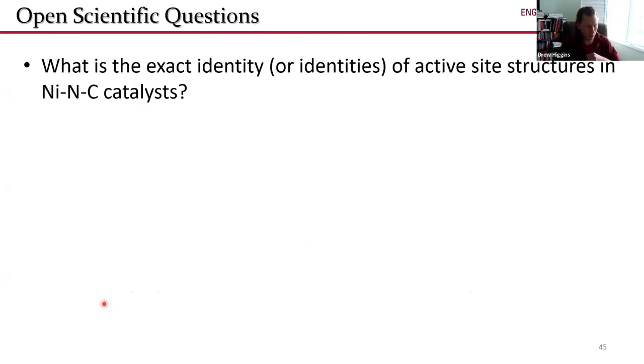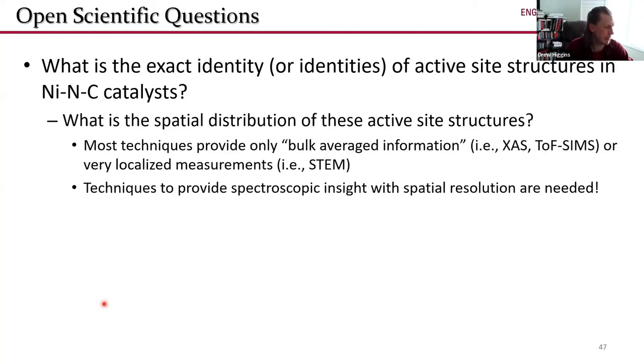And so we're starting to paint a picture of what the active site structures in these materials look like with a lot of advanced characterization. But then the next question is, what is the spatial distribution of these active site structures? Some of the techniques that I showed you, for example, X-ray absorption spectroscopy or time of flight secondary ion mass spectroscopy, are bulk techniques. So we're essentially getting bulk averaged information. We're scanning millions and millions of particles. And it's just saying, okay, it looks like these structures are present in these materials, but we don't know where they are. Maybe there's one particle in there that has a concentrated amount of these particular sites that we're characterizing, but it's not uniformly distributed across the catalyst.